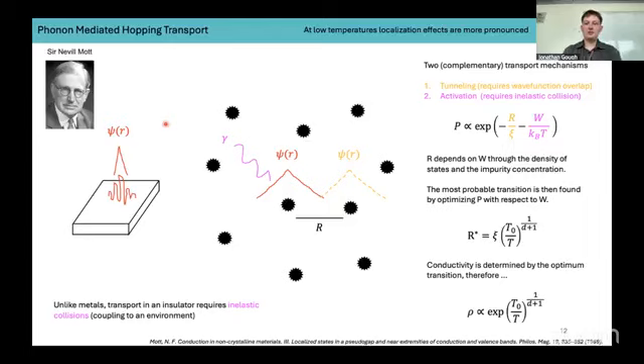So this idea of low temperature transport in a strongly disordered system was first developed by Professor Mott at the University of Cambridge. He considered a relatively simple model where you have some localized state on some potential minimum, say, and it's trying to be transported to a site a distance R away. To do so, it has two mechanisms. It can tunnel through the potential barrier, which is a quantum mechanical effect, quantum tunneling, or it can interact with the bath and be excited to the nearby state. These states will always be separated by some energy difference, W.